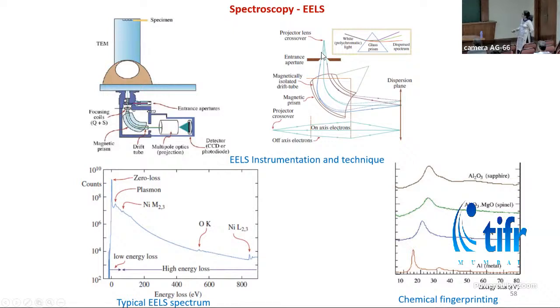The EELS spectrometer is nothing but the electron beam is passed through this aperture and it is bent by a magnetic field, and there is a magnetic prism here which is similar to a glass prism. Here the glass prism disperses light, here the magnetic prism disperses the electrons, and a spectrum is formed in the dispersion plane, where the x-axis is energy and the y-axis is the counts of electrons which have lost energy at that particular eV. This is the typical EELS spectrum, which contains the zero loss peak, which is formed by the direct beam. Then it has plasmon peaks, which mostly arise because of the thickness of the sample. Then it has low loss peaks, which give us information about band gaps, oxidation state, dielectric constant, etc. from the sample.